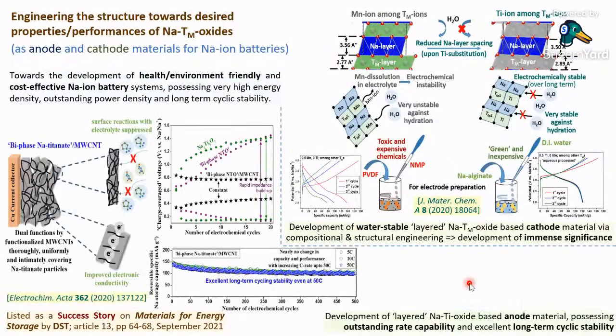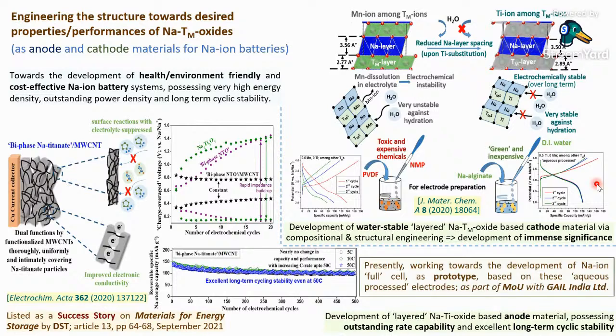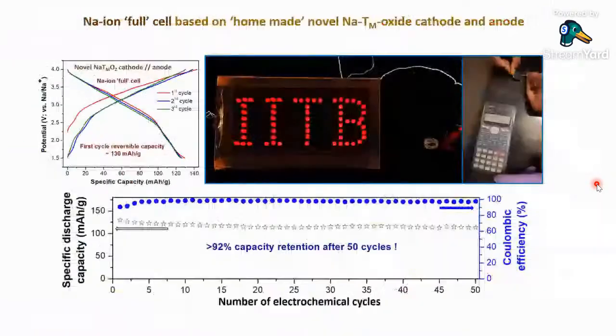Now, as a next step, we of course move towards the cell development. So we prepared another layered transition metal oxide, which is a slightly modified sodium titanate. It's a biphase sodium titanate, which also showed excellent cyclic stability and exceptional rate capability. One can see even at 50 C, one can get very good stability and very good capacity. So presently we are combining these two materials and trying to develop a full sodium ion cell, and then proceed towards prototype development.